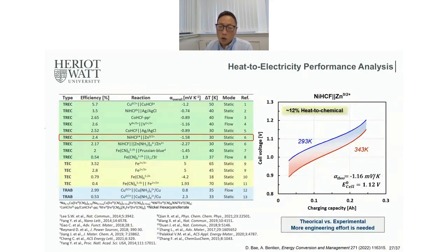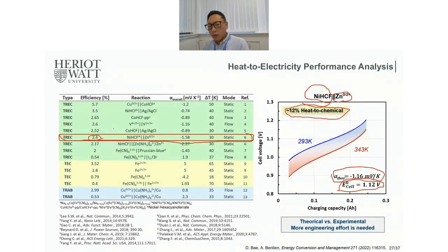One of our suggestions, according to our theoretical study, is the nickel hexacyanoferrate and the zinc metal system. By using these two in combination, we can have a cell voltage of 1.12 and a theoretical thermogalvanic coefficient of 1.1. And by using that, theoretically, we can convert 12% of the heat energy into chemical energy and electricity. Actually, this has already been tested by one of the U.S. universities, but unfortunately their efficiency was only 2.4. The main problem of this study was the very poorly designed insulation, and most of the heat was just lost during these two different temperature operating conditions.